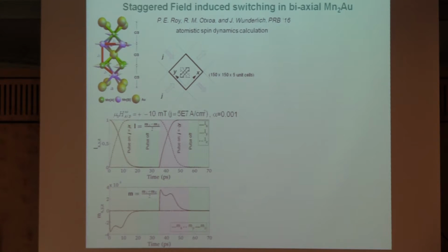Then sending another pulse of the same length along y, you can switch it back so that the L vector is along x. And if you look at the magnetization which occurs, indeed, for a very short time you start tilting the two sublattices in the z direction, which creates this exchange field that the moments can torque around.